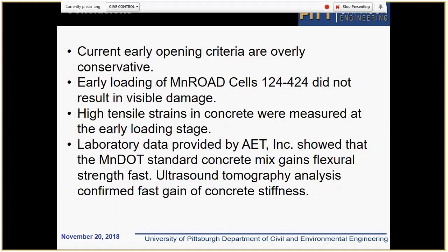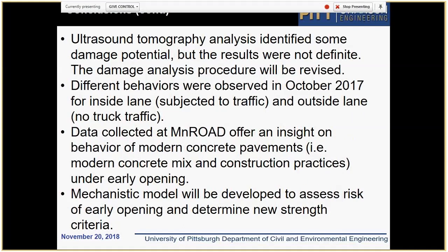And basically our conclusion is that the current guidelines are very conservative and can be relaxed. I'm not sure that we would like to recommend opening to traffic after 3-4 hours, but definitely there is no need to wait for 7 days for that, and of course the decision should be maturity based or stiffness based, not time based. But to really provide reliable recommendations, we need to conduct simulations and try to explain some of the effects we observed in the field, and that will be done later on when we start adjusting our models based on the information we analyzed so far, and that was collected at MnROAD.